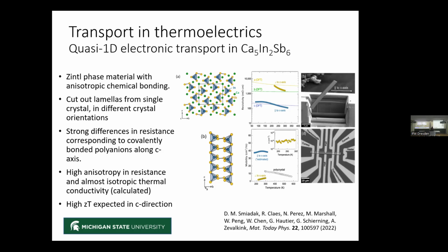And here the example goes about the technical issues that we found. These crystals can be grown as needles, but in this case they are undoped. This is a pretty interesting material, so they get very resistive. So the strategy to get the measurements done was to reduce the size of the material and fabricate lamellas with the focused ion beam, and then fabricate longer structures on top of them, and then perform the measurements. We were partially successful. We didn't do all that we wanted to do, but at least the conductivity and the Hall effect could be measured in two crystallographic directions, showing essentially a tremendous difference in resistivities.